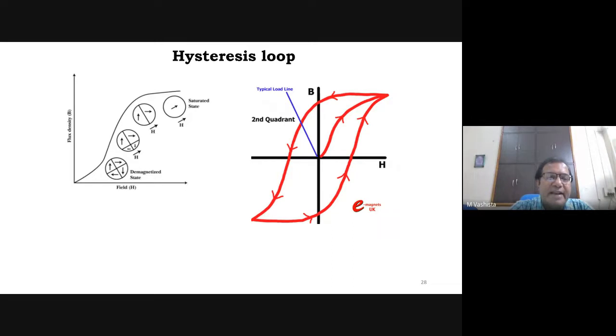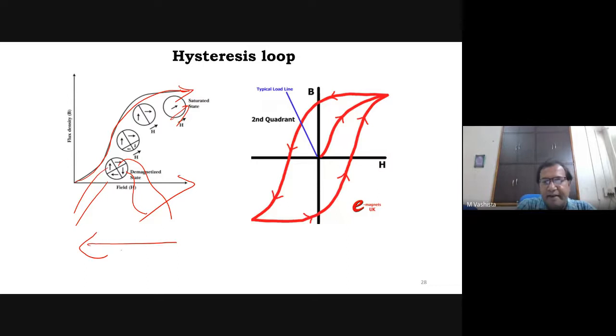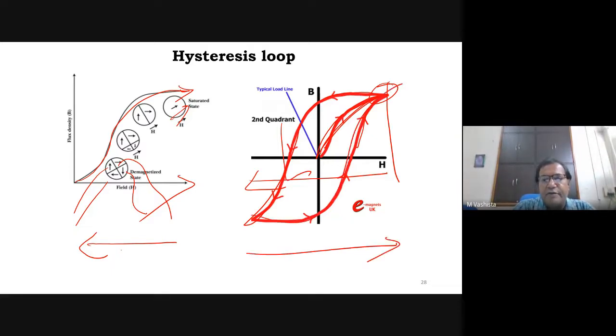Whenever I am going to magnetize any material, I will have to apply a magnetic field. When I apply a magnetic field, these domains of the material will try to align themselves. So the magnetization will increase like this. This motion will increase the magnetization inside the material, but what will happen if I reduce the magnetic field? From this point, if I reduce the magnetic field, this path will not be followed. The initial path, the path will be like this. And if I again increase the magnetic field, I will get this path. So this magnetization process and this demagnetization process will create a loop, and this loop is known as the hysteresis loop.